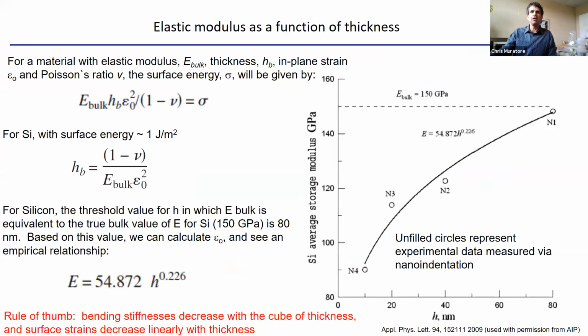So that's just a way to show what happens when you make these materials thin. This is not one atom thick, by the way, as my schematic in the past suggested. It's probably more like 80 microns thick. So that's about the limit. I can make silicon less than 100 microns thick, and it becomes fairly flexible. I can make it way thinner than that, and it becomes really, really flexible.